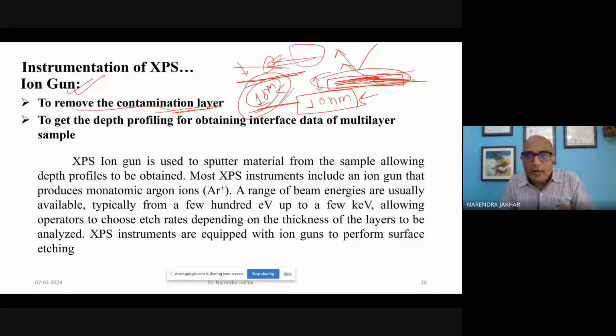We can remove the sample layer by layer, and this is very helpful when we are working with devices or heterojunctions. If we want to know the exact material chemistry at the interface of two layers of your device, we can use the ion gun to sputter the first layer, reach the interlayer, and then sputter again to reach deeper depths where two different layers join together, and we can study the surface chemistry of the specimen there. Usually we use an argon plus ion gun, and monoatomic argon ions are used in the ion gun.